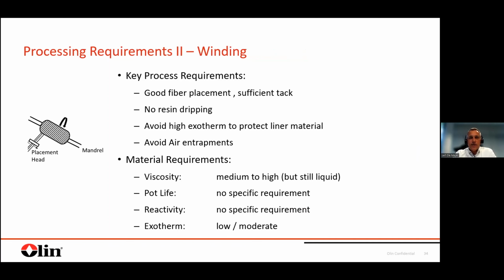So let's look at the second step, the winding process itself. Basically, what you want to see here is a good fiber placement and a sufficient tack of the material. You also don't want to see resin dripping, for two reasons. First of all, you're paying for the material. But secondly, of course, this would impose a lot of cleaning requirements on your manufacturing environment. So this should be avoided or minimized as much as possible. You still do not want to see high exotherm behavior in this step, in order to protect the liner material, which, as I mentioned, is typically a polymer material with a certain temperature stability. You cannot afford to exceed the temperature stability of your material. And last but not least, here you also want to avoid air entrapments.